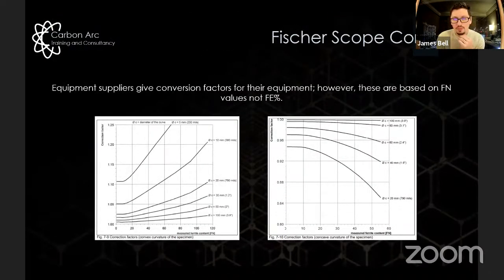Now, when we went back, of course, looked at the equipment, got as much data as we can, we could see that the scopes came with a conversion chart. Now, this was to take your reading and then have a percentage increase on your reading, basically on wall thickness and diameter of tube. Now, one of the main issues for us here was all of the conversion charts are based on ferrite number, not ferrite percentage. So for our project, we had to have a ferrite percentage pass or fail, not ferrite number.